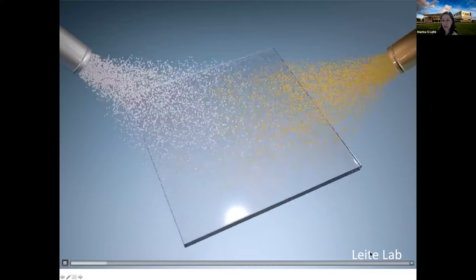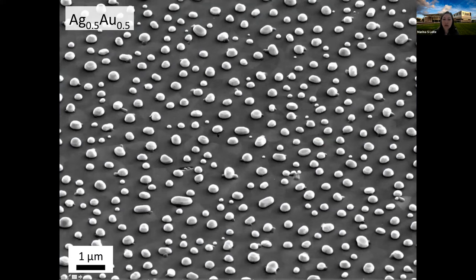But for now, okay, this is the result. What I'm showing you here is a scanning electron microscopy, an SEM image, of a large area of how these samples look. I like showing this large area precisely to recognize that it's not a super uniform process. You can see that we have some incomplete Ostwald ripening, and some of the particles coalesce, but overall the size distribution is fairly narrow, considering that this method can be easily scaled up. It doesn't require any complex nanofabrication methods, such as EUV lithography, or any type of templated method.